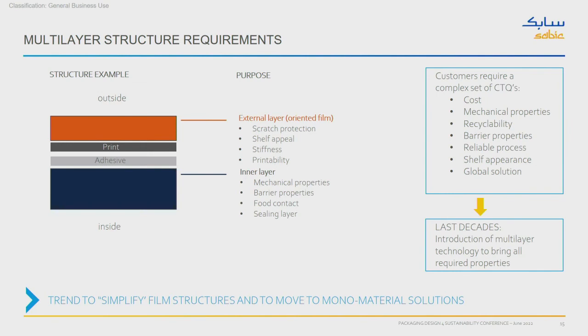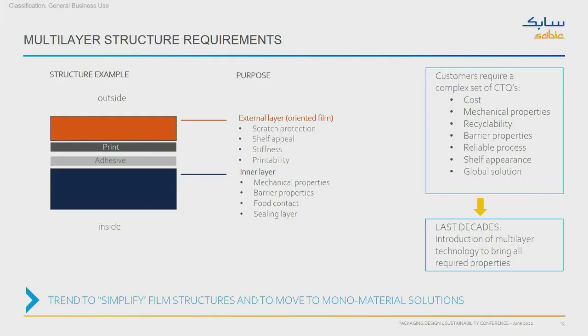And that is in principle why we build up a certain film structure as a laminate, because of the functionalities, and we cannot put them all into one layer. So we need multiple layers, but preferably out of one material. The majority of the laminates used at the moment in the market are multi-material, so polyester PE, PP PE laminates, PP PP also. But we prefer to change that into a full polyolefin structure. And that's why we developed this BOPE, biaxially oriented polyethylene, to use in these types of laminates.